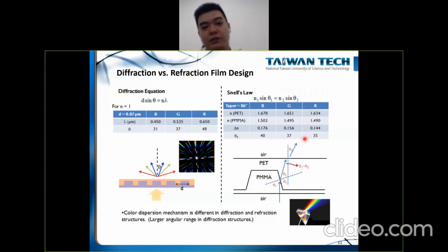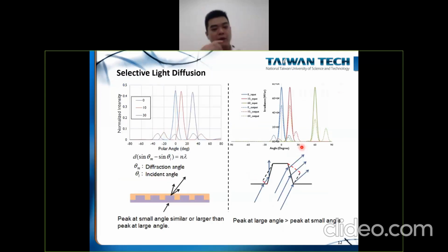Okay, so you can see in this case, actually the blue light will be refracted to like 40 degree, and the red light will be refracted to 35 degree. So this color dispersion mechanism for these two may be different. Why? Because you can see that for this type of mechanism, the blue light actually diffuses to a smaller angle, but for this type of structure, the blue light actually diffuses to the larger angle. And we try to compare these two mechanisms for the design concept.